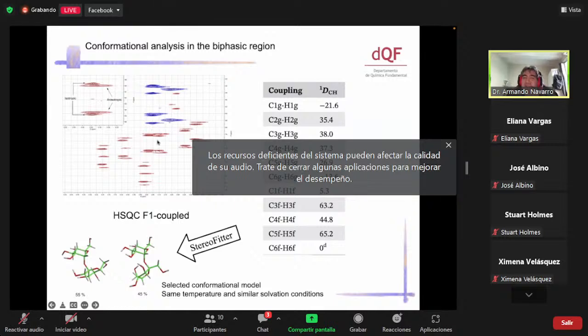And a nice thing is that when we put saccharose into the system, the biphasic region close to here was stabilized. So we could see isotropic and anisotropic together. And because the dipolar couplings in these systems are relatively large, we were able to measure the dipolar couplings in the biphasic region. In one single spectrum, you get the isotropic and the anisotropic signals. So this is very convenient because you have exactly the same temperature. And in chromonic phases, in principle, the solvation conditions compared to other lyotropic systems are very similar in the isotropic and in the anisotropic phase. So this is a good procedure to do fine conformational analysis.